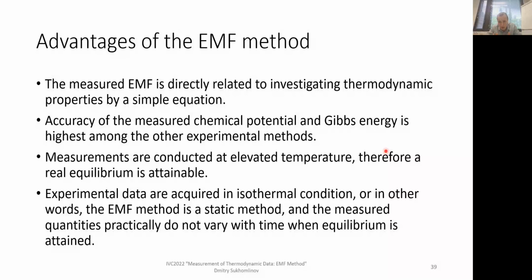Also, it is relatively quick, but I must say it depends. When we work with oxygen solid electrolyte, those measurements are quicker because, as it has been said, temperatures are 600 and above, 1000 and then even higher. So equilibration is quick. Within a day, we might get a couple of data points. We might equilibrate our system, our galvanic cell, at a couple of different temperatures.